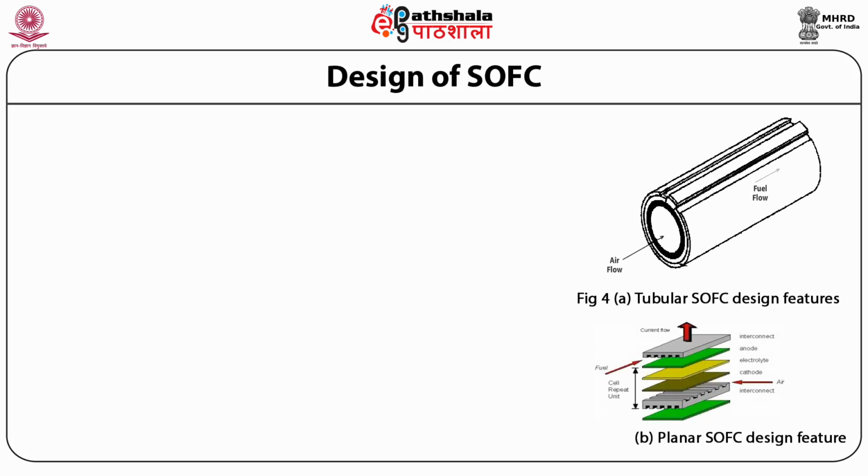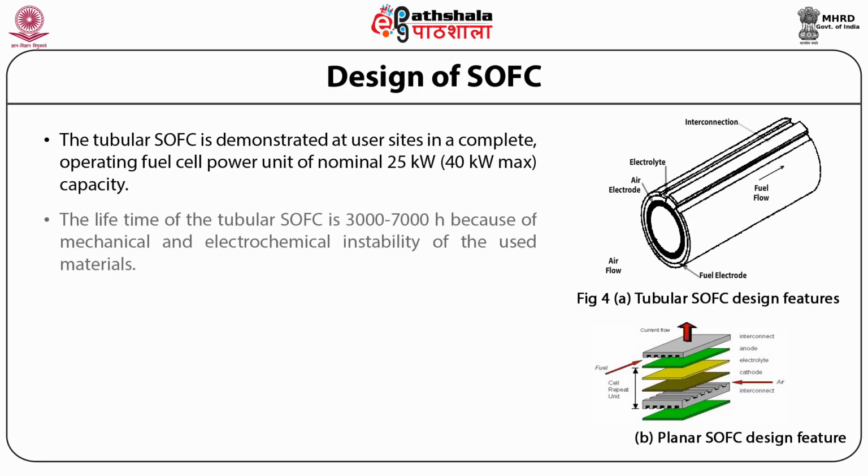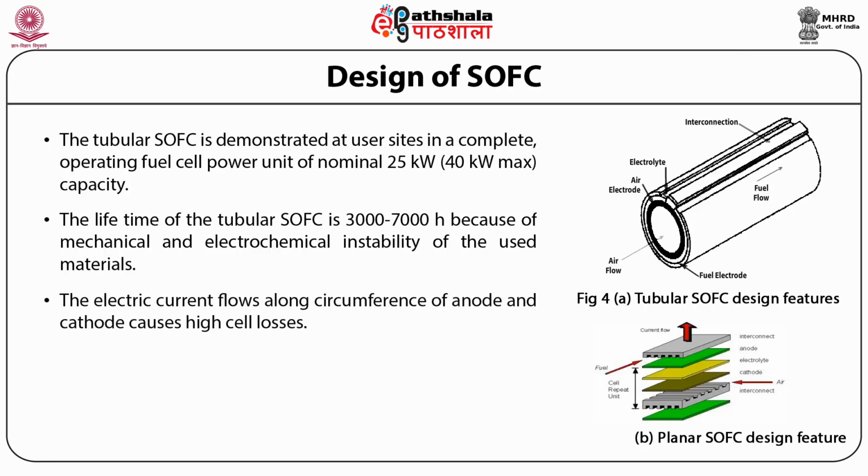Design of SOFCs. First is the tubular SOFC. The lifetime of the tubular SOFCs is 3000 to 7000 hours because of mechanical and electrochemical instability of the used materials. The electric current flows along the circumference of anode and cathode, which causes high cell losses.